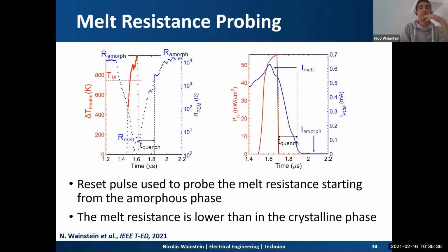Also, to prove that the melt resistance is smaller than the crystalline phase resistance, we use a reset pulse to probe the melt resistance starting from the high resistance state. So we start at the amorphous, high resistance state. As the temperature rises, the resistance decreases down to the melting resistance, which is lower compared to the crystalline resistance. And then when the pulse ends, the quenching or cooling process is triggered, returning the phase into the high resistance state. This way we can also characterize the quenching time of these devices.